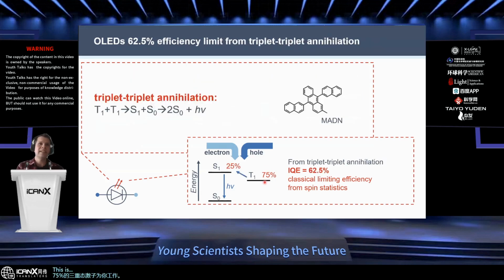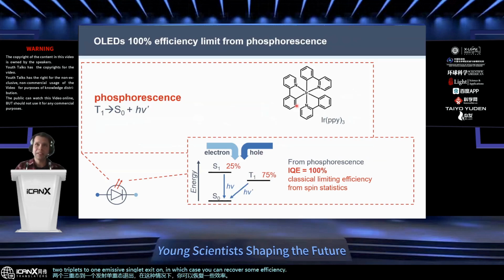This has been sorted out to some extent in industry. So one method is to take a delayed fluorescence process called triplet annihilation that converts two triplets to one emissive singlet exciton, in which case you can recover some efficiency. Something else you can do is to try to promote phosphorescent emission from the triplet excitons. This is also something that people are employing in industry, especially for red and green colors, and this works pretty well.